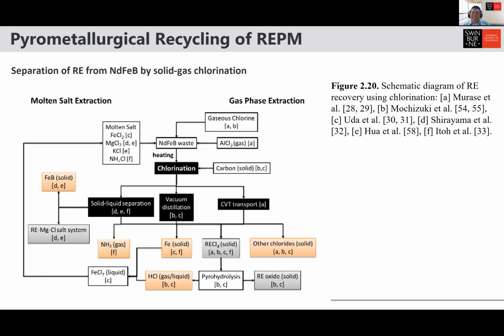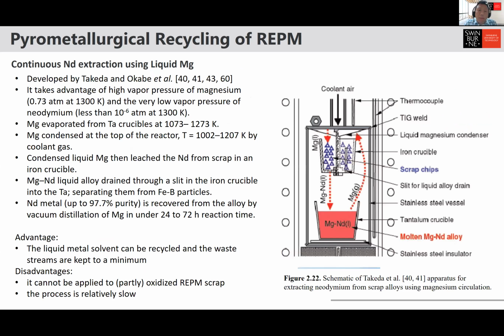Another interesting process is using liquid magnesium as a way to extract neodymium from the magnet, right? So this is quite an interesting process. It's developed by Takeda and Okabe. In essence, it takes advantage of the high vapor pressure of magnesium, about 0.73 atmosphere at 1300 K, but also the fact that the vapor pressure of neodymium is quite low, about 10 to the minus 6 at 1300 K, right? So the process is shown on the right.